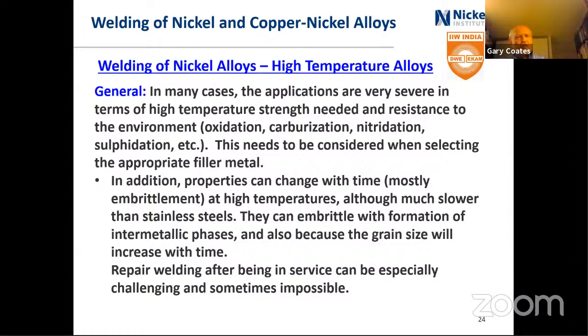I'm going to get now more into some specific alloys and specific conditions here. I'm not going to talk a lot about the high temperature alloys. I just have one slide about it. They're used because of their high temperature strength and their resistance to the environment. It can be different environments, and different alloys are used when it's oxidation versus carburization or nitridation or sulfidation. All that needs to be considered when selecting the filler metal. You want filler metals to have the right strength at the high temperature. You want them to have the right resistance to the environment.